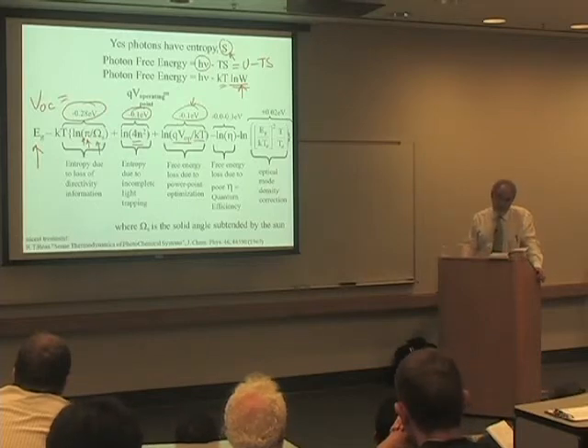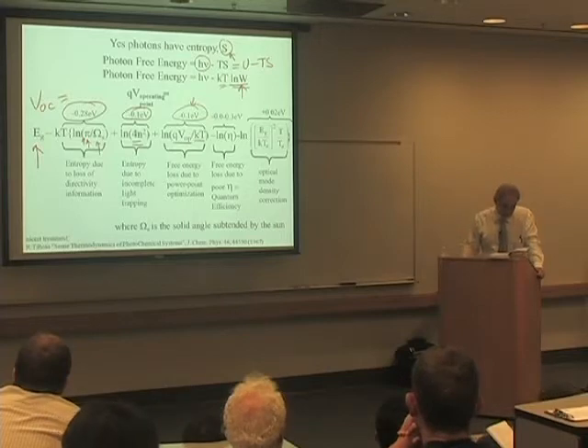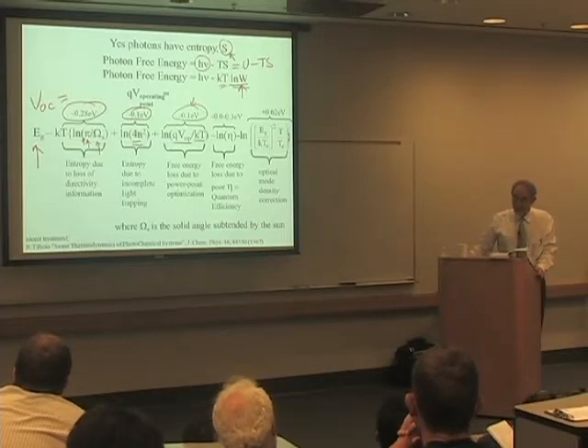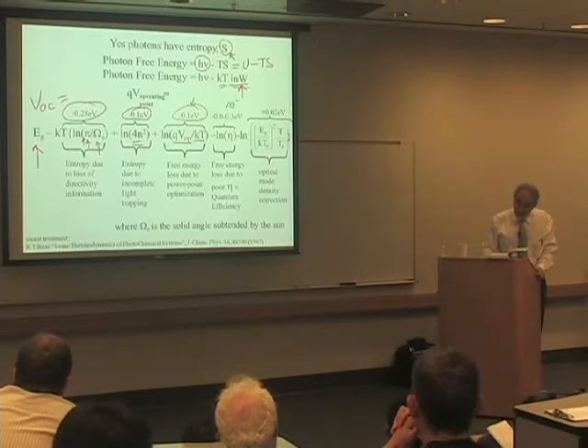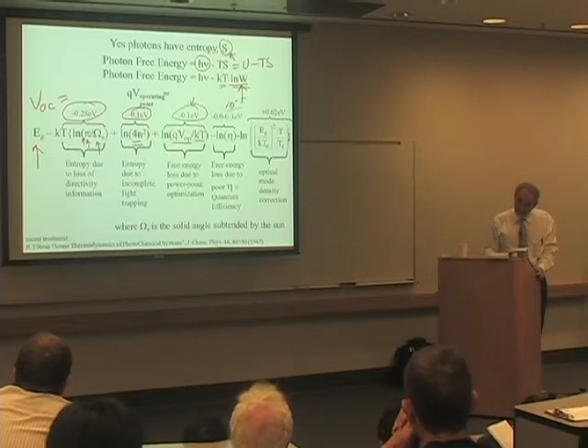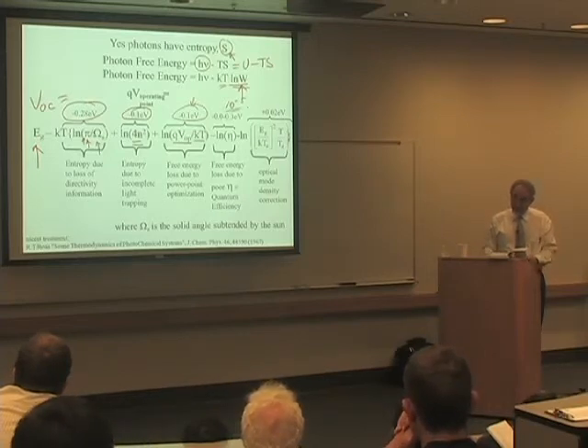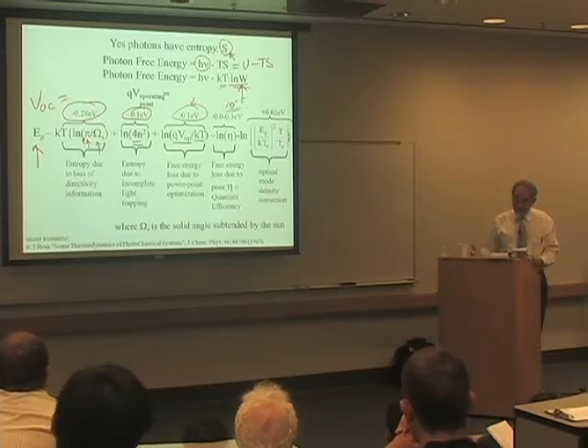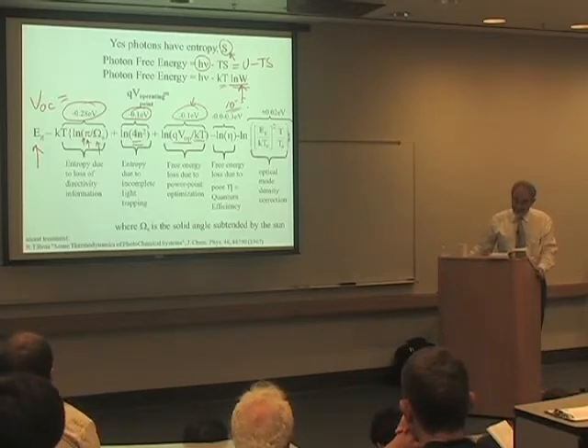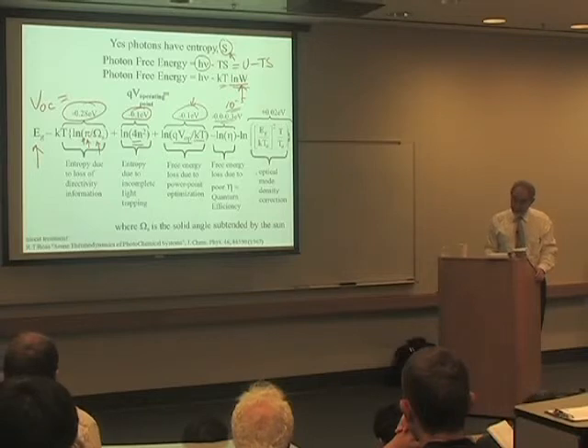But we don't often have that. Often we have extremely low. And there are many types of solar cells. The people who work on them are not even aware of their external luminescence efficiency. And so let's say it's 10 to the minus 5, which it could easily be for certain very poor quality solar cells. So kT log of 10 to the minus 5 could be as much as 3 tenths of a volt. So you keep losing and end up with pretty low voltage.